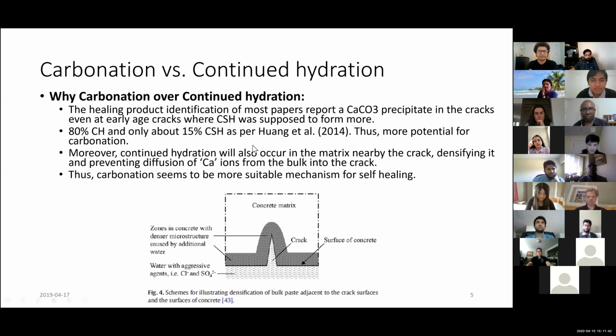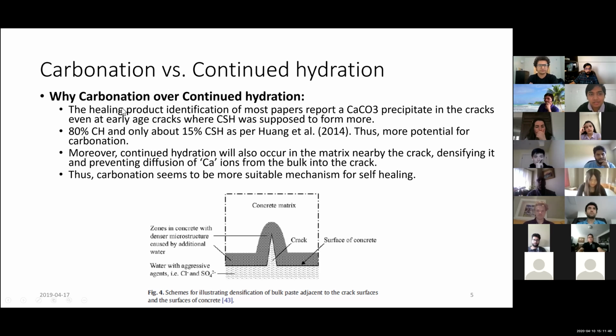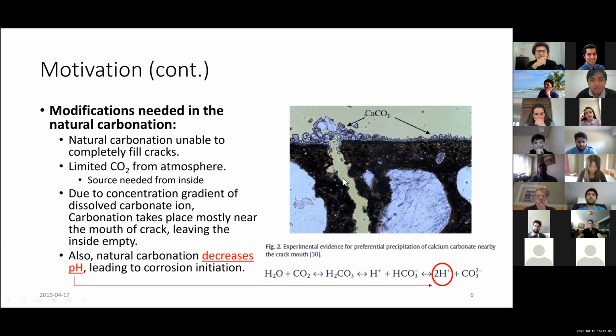In terms of the comparison of the two mechanisms, I would like to give you an overview that carbonation has been reported to contribute up to 80% of the healing, and the rest, roughly 20%, comes from continued hydration. So I'm going to skip this. There is some improvement needed in carbonation though, because in natural carbonation, only the surface usually gets to dissolve carbon dioxide and precipitate. So there is very little precipitate deep inside the crack, and more precipitate on the surface, and this blocks further diffusion of carbon dioxide inside. So you rarely can fill a crack using just natural carbonation.